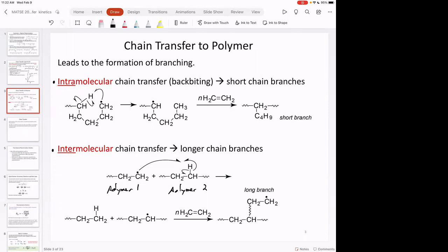And we know that polymer 1 is the growing chain. Why? Why is polymer 1 the growing chain? How do we know that? It's got the radical. So, you know, this is polyethylene probably. You know, there's no substituted carbon in polyethylene. It's just CH2, CH2, CH2. So that's where the radical has to be. So polymer 1 is the growing chain N. Polymer 2 is just a polyethylene molecule with no growing chain that's just sitting there minding its own business.